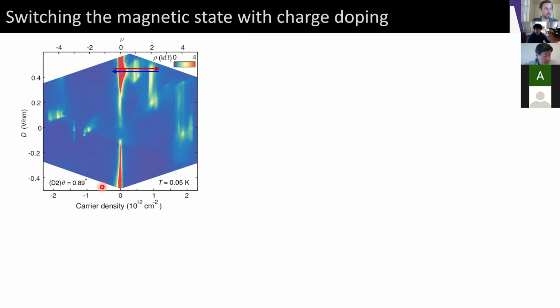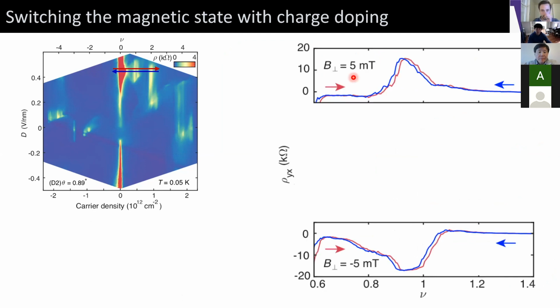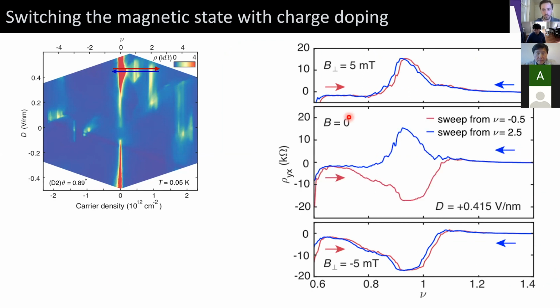Okay, so one quite curious effect that we see in this sample arises when we sweep the doping back and forth across this quarter-filling state. So we do this with a small magnetic field of a few millitesla. It doesn't matter which direction we sweep. The sign of the magnetization is set by the sign of the magnetic field. But then somewhat bizarrely, when we do this very, very close to 0 field, we can actually switch the magnetic order depending on which way we sweep the doping.